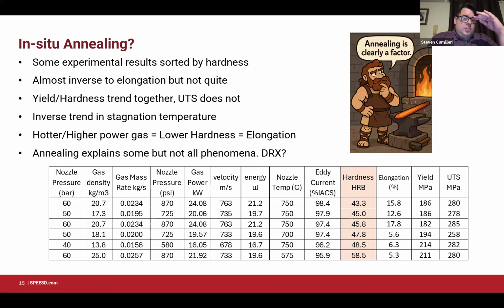So what I've done is I've sorted these results during a variety of temperatures and pressures. I've sorted them by hardness. So that's the orange column there, from low to high. And so, of course, what we see at first is that some of the higher powers in the gas correlate with the lower hardness, and the higher nozzle temperatures also correlate with the lower hardness. And indeed, it's not quite monotonic, but you'll see that the elongation is also correlating with the lower hardness.